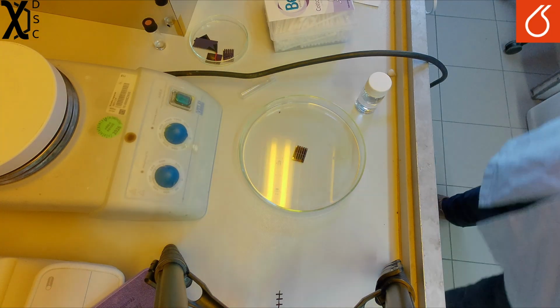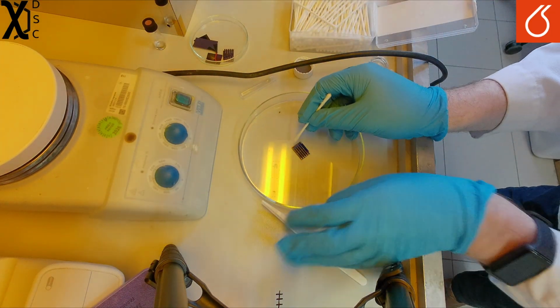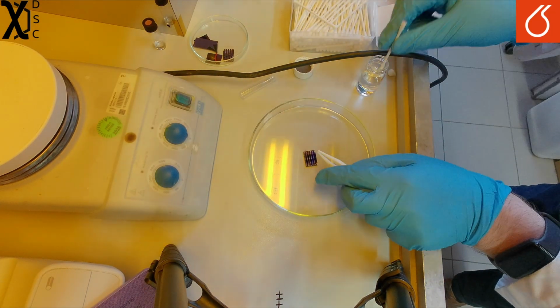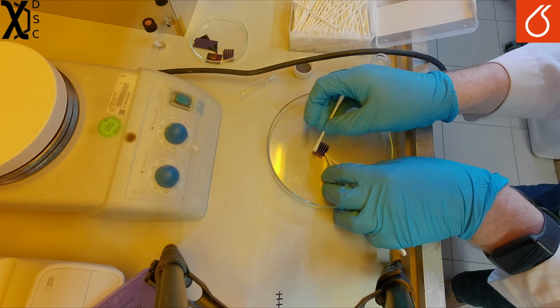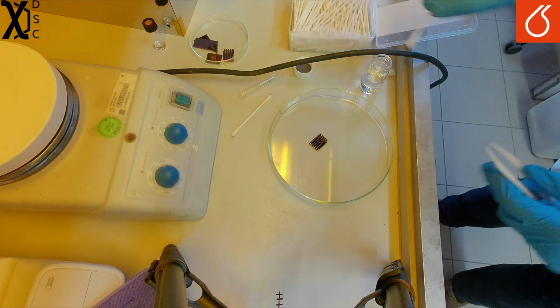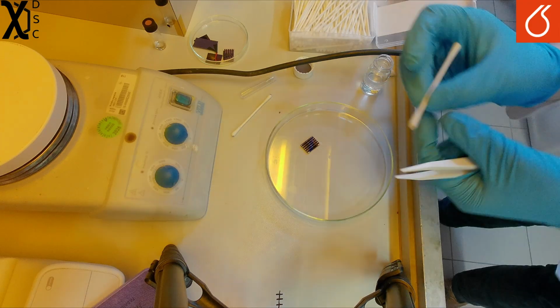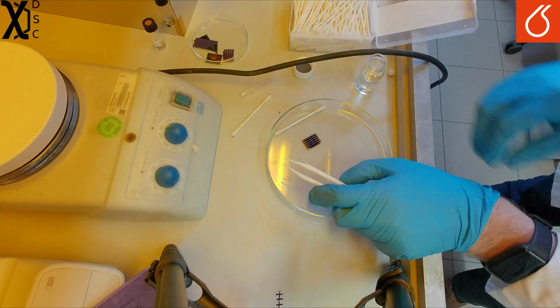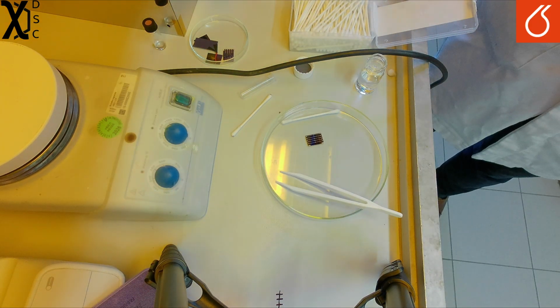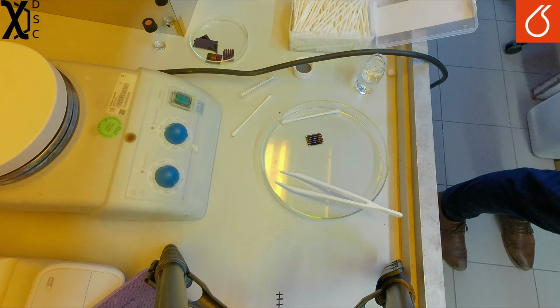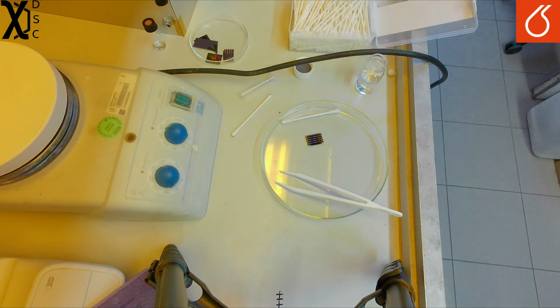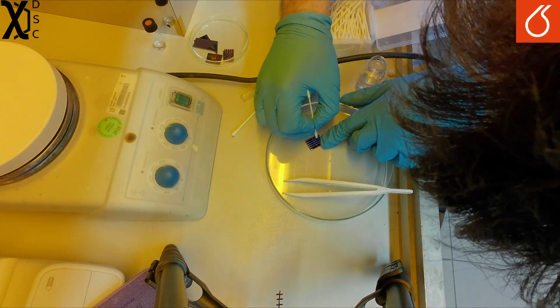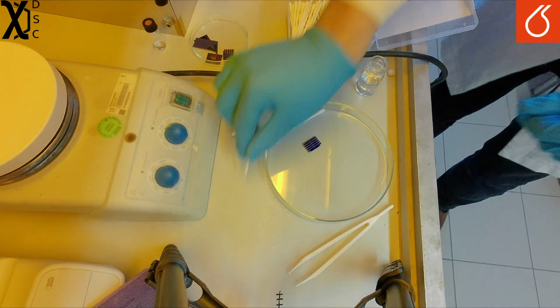After depositing, it is necessary to remove the excess material which covers the contact pads. That is, the parts of the substrate we wish to attach our electrodes to. In order to do this, it is necessary to wet a cotton bud with a suitable solvent and wipe the compound off. A suitable solvent would be one which readily dissolves the compound. The final OFET is thus made. It may now be used and tested. The testing and contacting of the substrate will be covered in another video.